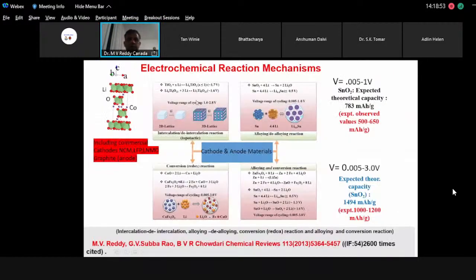Intercalation and de-intercalation is the most popular mechanism in commercial batteries, including our laptops, iPhones, and commercial EV vehicles. On the anode side, graphite is more popular because we don't see much volume variation during charge-discharge cycling. Tin and silicon undergo an alloying and de-alloying mechanism. Here is the importance of nanotechnology: the material should be very small in size and dispersed in a carbon matrix.